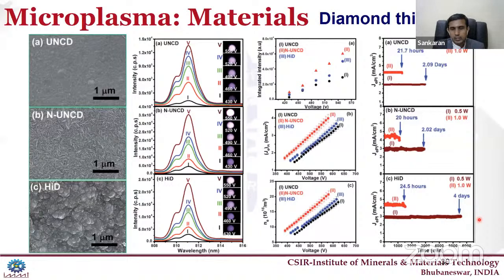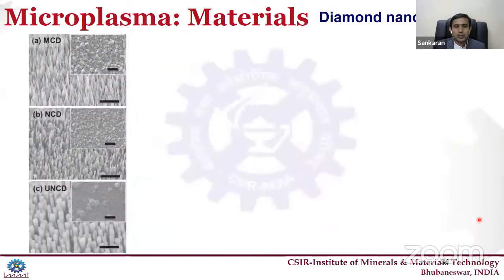It keeps on in a stable way. So the current is also a very constant emission, and the plasma intensity is also stable. So diamond thin film is a very good cathodic material to be utilized for these microplasma devices. Also, we have carried out work with different nanostructures in these diamonds. One-dimensional nanostructures were fabricated using a plasma reactive ion etching method.